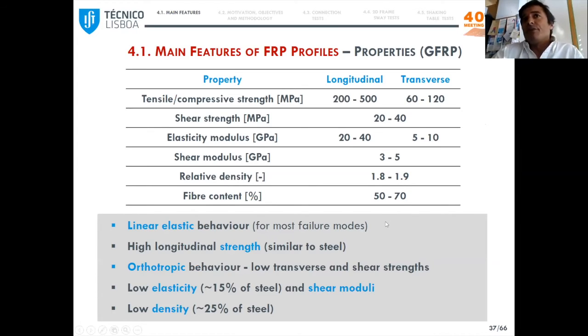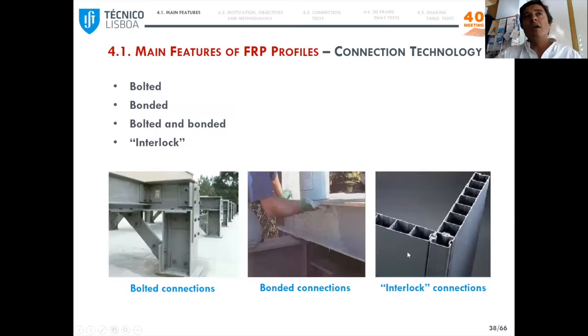First of all, let me recall the behavior is linear elastic for most failure modes. So the longitudinal strength is similar to several steel grades, but the behavior is orthotropic. So lower strength in the transverse direction, low shear strength, and also low values of elastic moduli when we have glass fibers. In terms of connection technology, that is relatively underdeveloped.